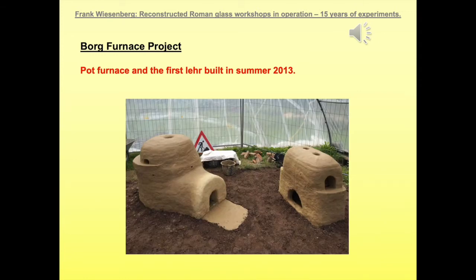The building also was pretty hard due to the weather conditions. In 2013, it was a very, very hot summer, and building wasn't too nice inside a transparent plastic tent at the Villa Borg. But nevertheless, the pot furnace and the first lehr were finished by September 2013, and after drying out and with covering off all the cracks which would appear during the drying out process, they were started in the end of September, beginning of October for a test run.